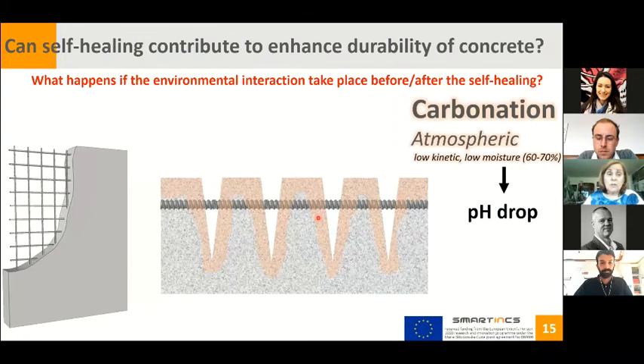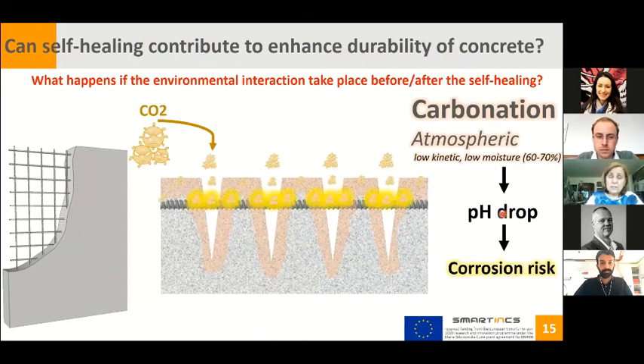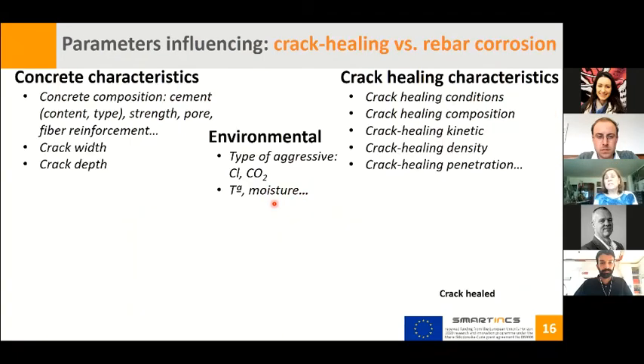In the case of carbonation, we can have a very similar performance. Carbonation, in the atmosphere, is low kinetic, low moisture, and the pH drops, and also the corrosion initiates, but as we commented, it is more general, extended on the surface. We can have a similar problem when we are thinking of avoiding the corrosion initiation at the rebar level if the self-healing of the cracks is allowed. To finalize, I want to analyze them through this experience and analysis.